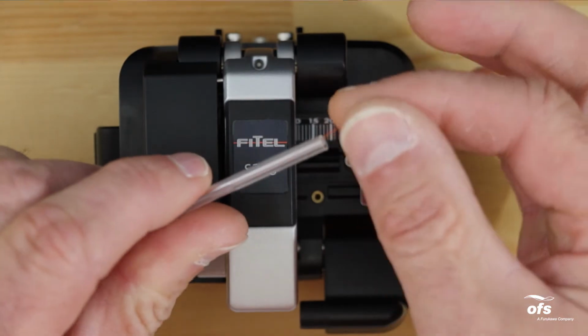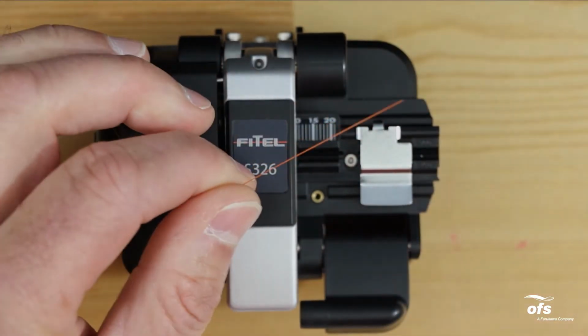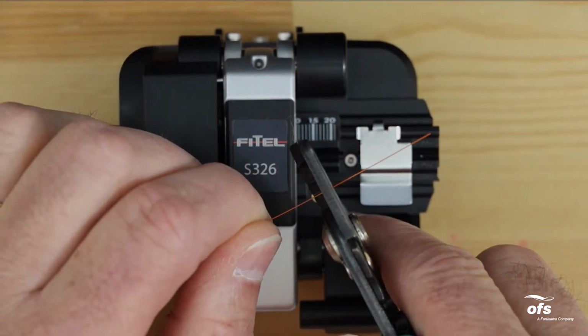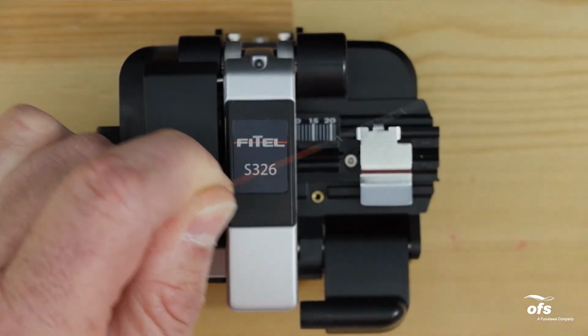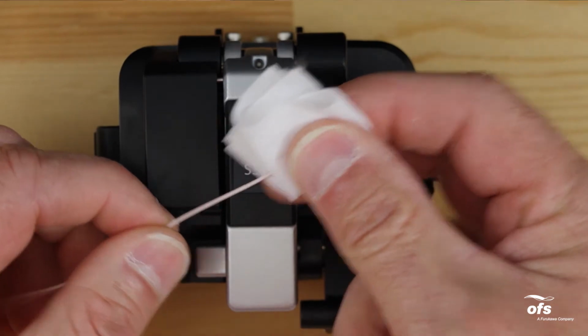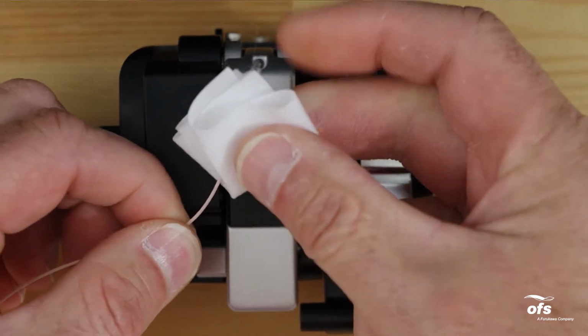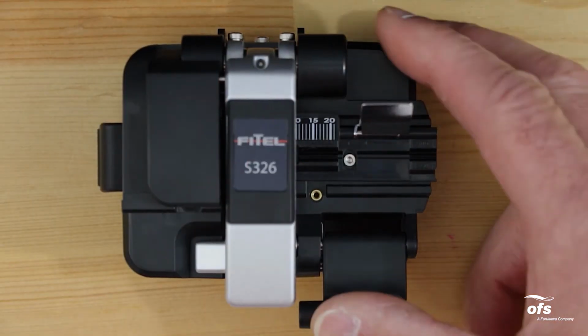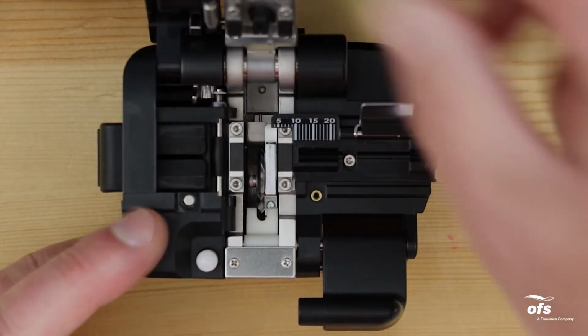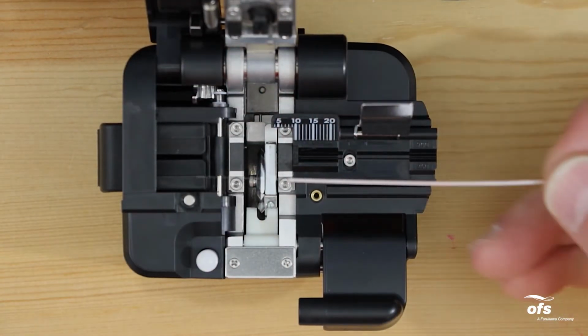If you are using 250 micron fiber coating, strip approximately 30 millimeters of 250 micron coating from the end of the fiber, leaving bare glass. Wipe the bare fiber with a lint-free wipe soaked with fiber prep fluid. Open the fiber cleaver, place fiber onto the single fiber adapter, and cleave to 10 millimeters.